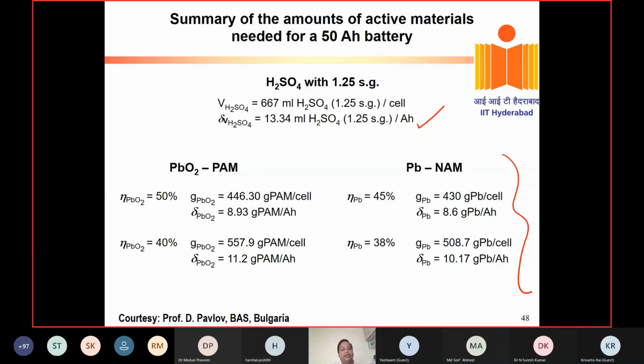So efficiency, I was telling, the efficiency of lead acid battery. It's not that all the materials are utilized for electrochemical reaction. Instead of 240, I told you around 200 to 240 milliampere hour per gram of lead oxide, but we get around 100 to 120. So it's around 40 to 50% efficiency. Accordingly, if it is 50% efficiency, around 10 to 11 gram for PbO2 and 10 gram for Pb, and around 13 ml of sulfuric acid is required for lead acid battery fabrication.